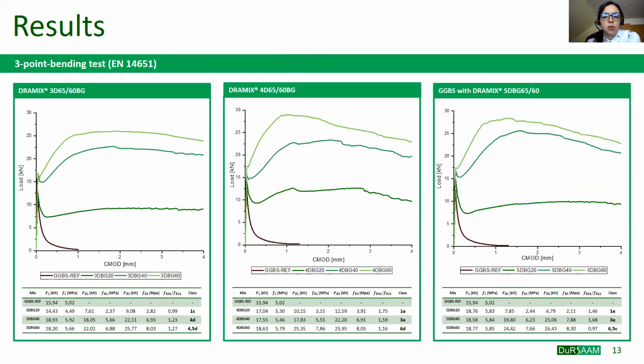In this slide, the load CMOD (crack mouth opening displacement) diagrams obtained directly from the 3-point bending test are shown for each fiber type. As we can see, for all the fiber types, an increase of fiber content corresponds to an increase of the residual flexural behavior. However, if the fracture energy is almost double with an increase of fiber content from 0.25 to 0.50, increasing the fiber content from 0.50 to 0.75 does not lead to a similar increment of fracture energy.